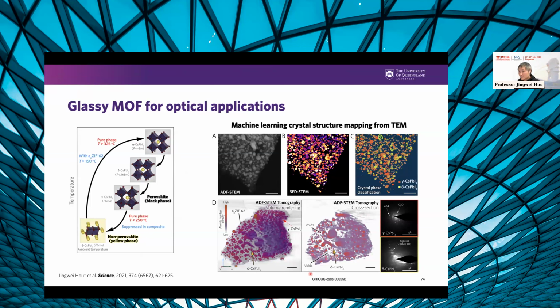When I look at the stereotypical perovskite, cesium lead iodide, which people use for solar panels, I immediately see the problem with the material. I draw a phase diagram for this material. It's not stable against almost anything: water vapor, light, or oxygen. But the big thing is that it's not really stable against water. Against temperature, at room temperature it is a non-perovskite, what we call the yellow phase. So we have to heat it up to about 325 degrees to allow the crystal phase transition to a perovskite phase. But during cooling, it will spontaneously get back to the yellow phase, which is useless, at a temperature of 250 degrees. So I thought about how we can solve the problem.